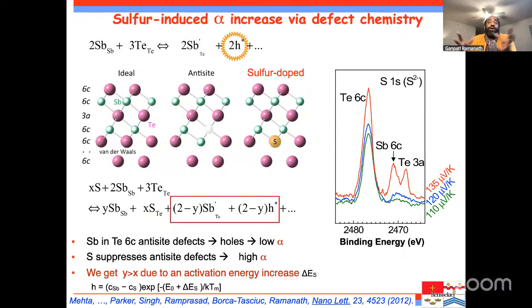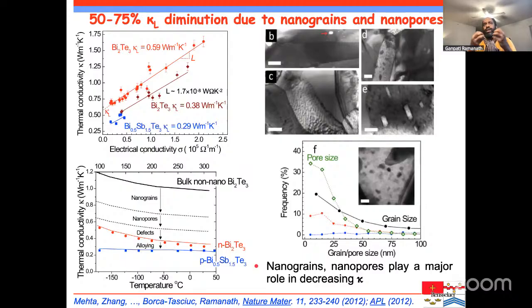So this is what we found by a whole bunch of spectroscopies and microscopies. I've shown one key figure on the right side, which we did by synchrotron spectroscopy, X-ray photoelectron spectroscopy. And this essentially gives us an amazing figure of merit. So that was one aspect of many things where we could improve properties.